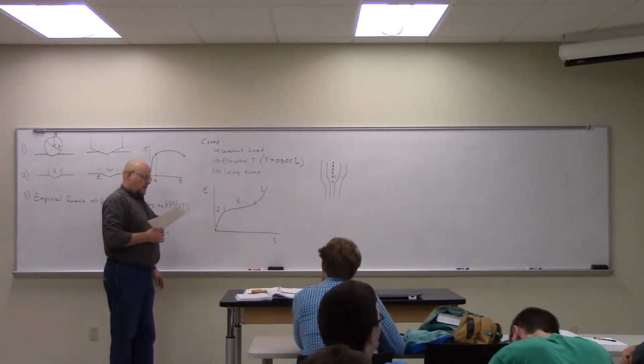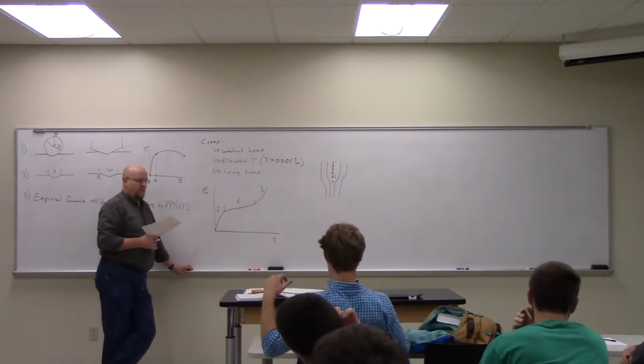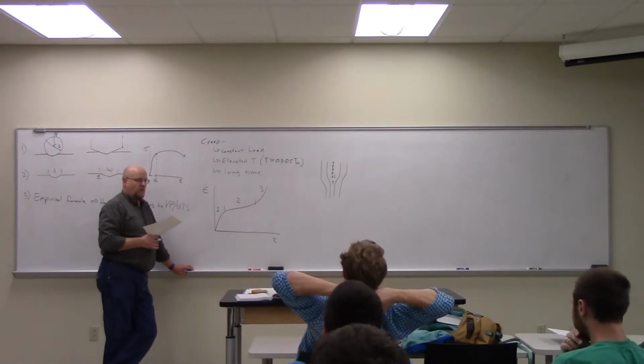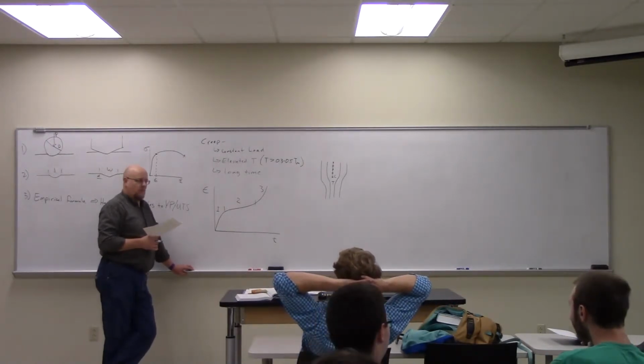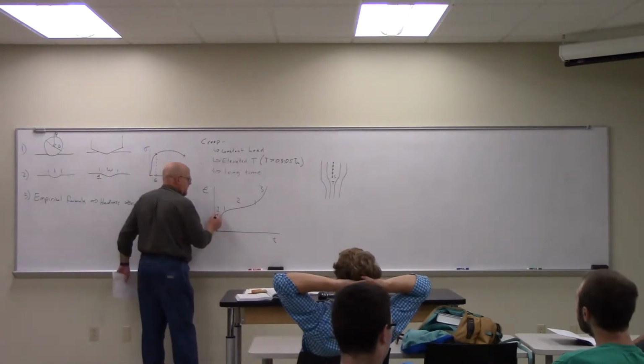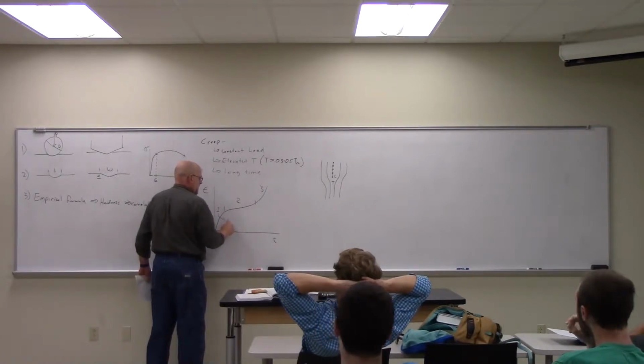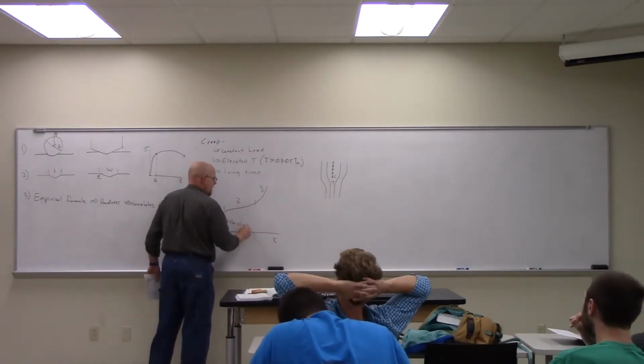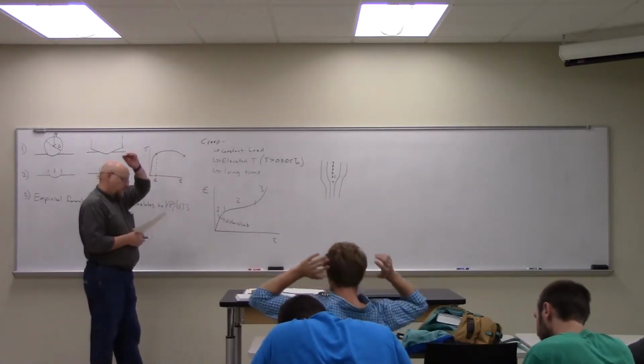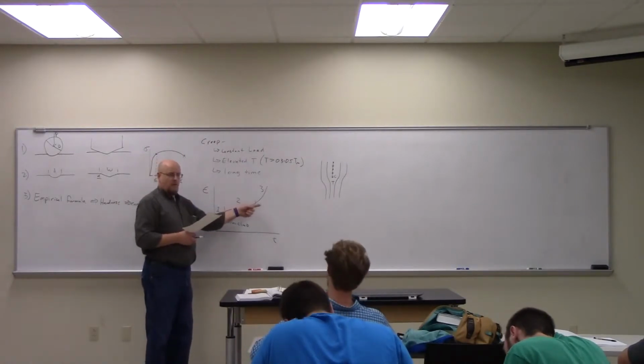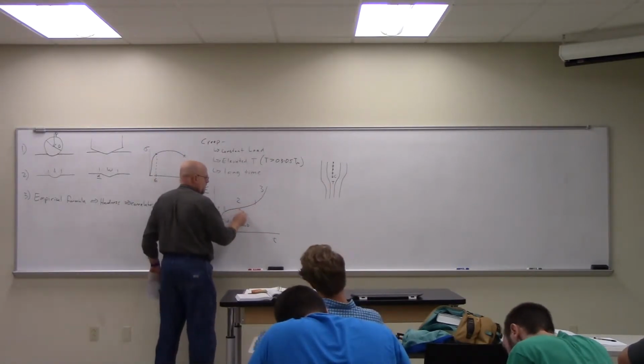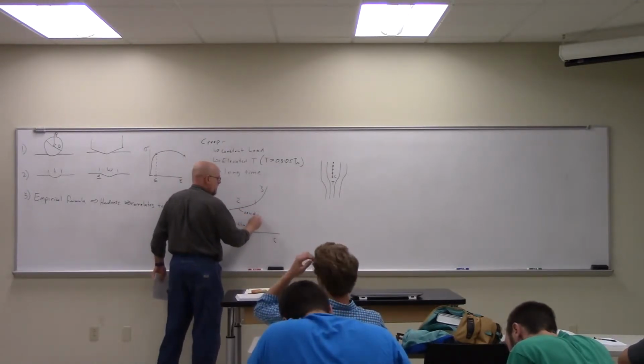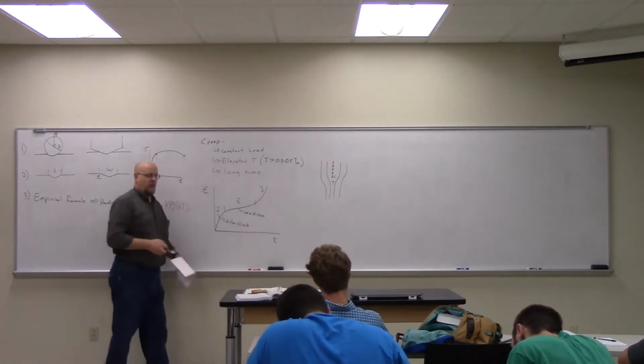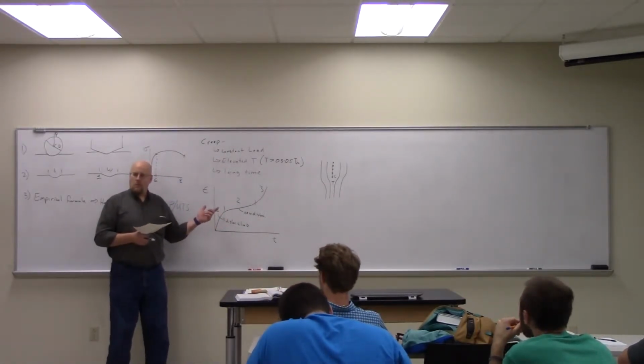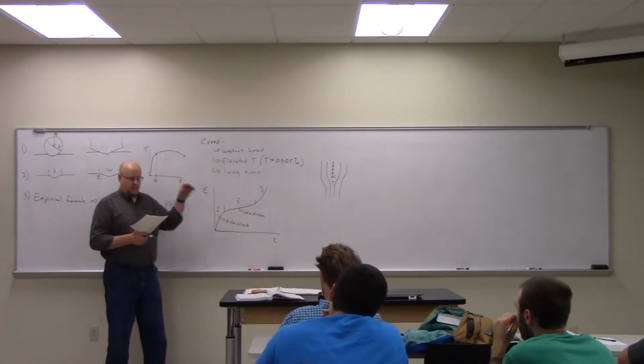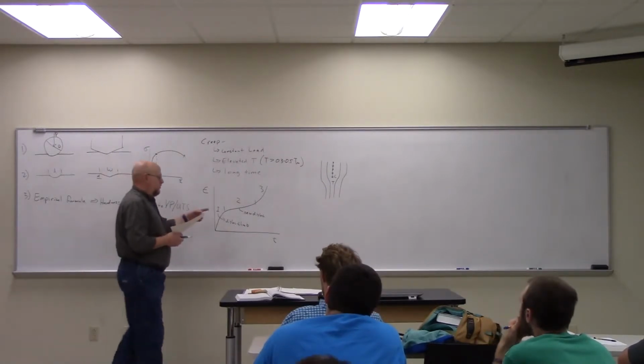Okay? What are each of those sections? There are 3 different phases of creep: stage 1, stage 2, and stage 3. Stage 1 is the area where I have dislocation climb due to vacancy formation. In this section, it slows down because I create new dislocations that exactly balance, or almost balance, the dislocation climb. So the dislocations are able to move around.